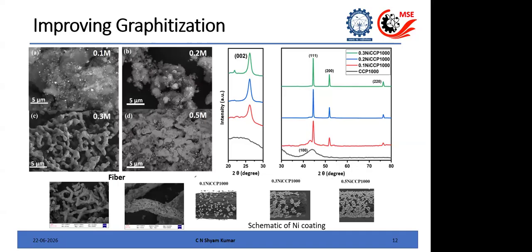Now, till now what we have done is that with a normal single pyrolysis, we were trying to increase the graphite content until 1000 degrees Celsius. But that is not sufficient all the time. So what we do is that we use a catalytic method to increase the graphitization. And with Raman and XRD, we could understand now that it is highly graphitic.